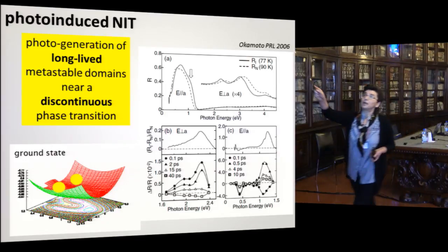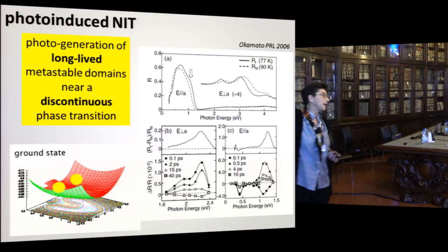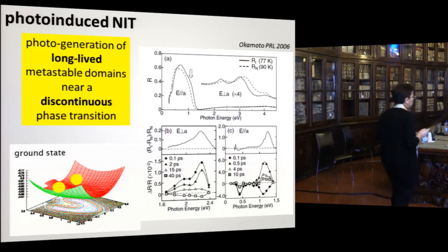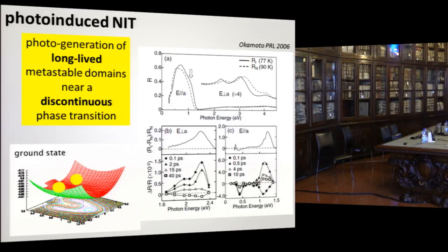When they go in the low temperature phase, 77 K, basically the charge goes to 0.7 or roughly so. So you have 0.7 plus and 0.7 minus. And this means that on average, in each donor acceptor pair, 0.5 electrons is transferred. Okay?